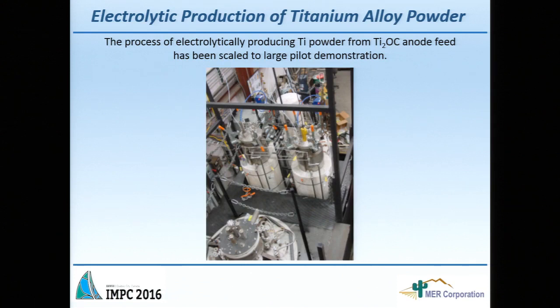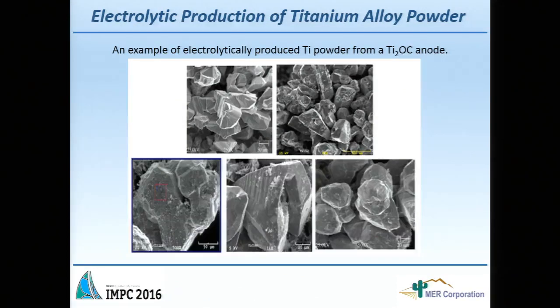This pilot plant ran for I don't know how many months. We have a joint venture with Timet, and that plant was disassembled and shipped to Nevada. One of the issues is really the size of the titanium powder you produce. The bigger the size of the powder, the more applicable to the powder metallurgy or additive manufacturing, plus it's going to have less impurities, right, and less oxygen. And as we could produce powder fairly sizable, from 20 micron to 50 micron. Again, depends on the current density, depends on the operating condition of the cell.